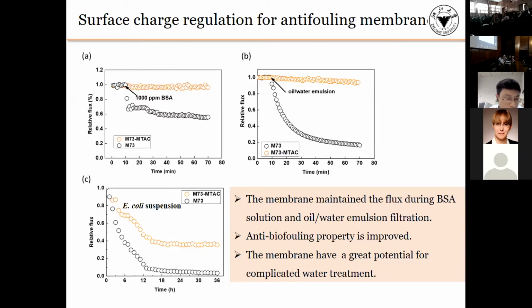Because we introduced the MTAC onto the membrane, the hydrophilic component further improves surface hydrophilicity. Meanwhile, MTAC neutralizes the surface charge. In addition, a polyampholytic copolymer was formed. Such a copolymer is recognized as an antifouling component.